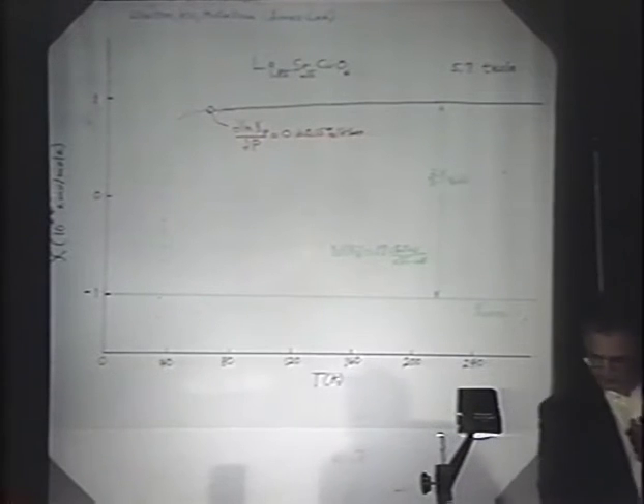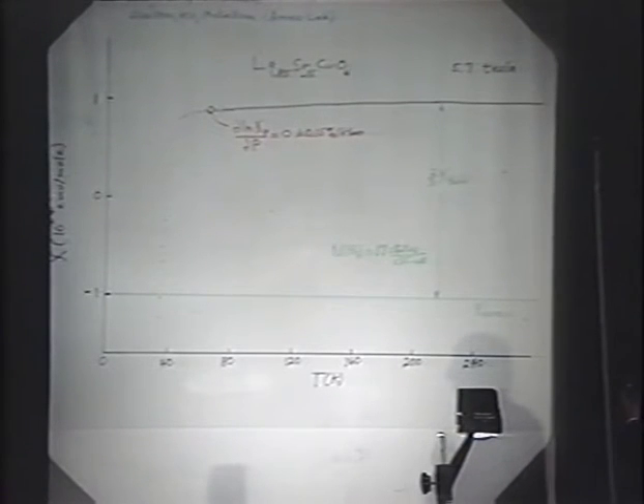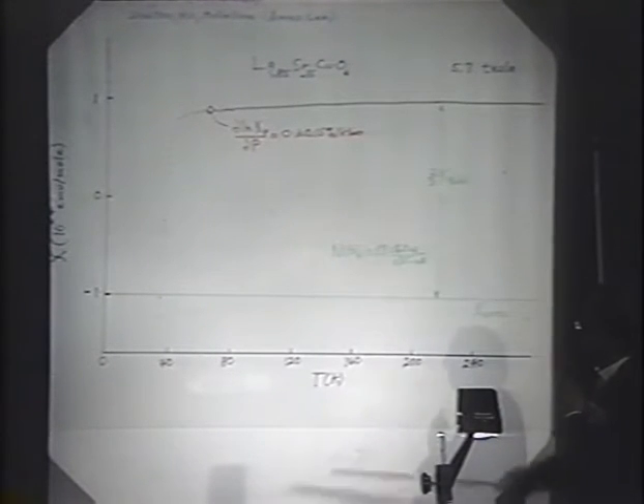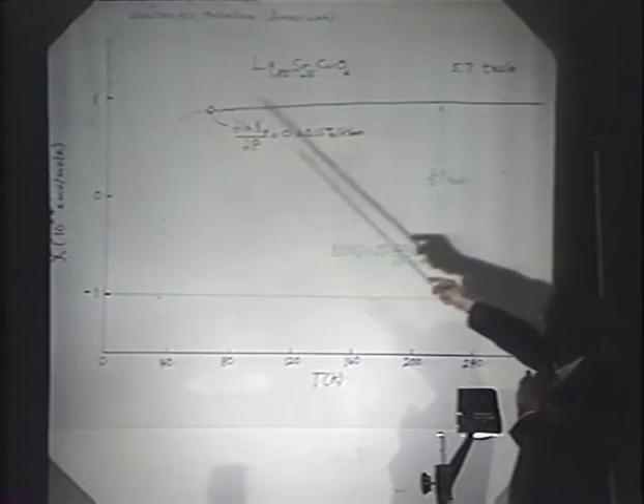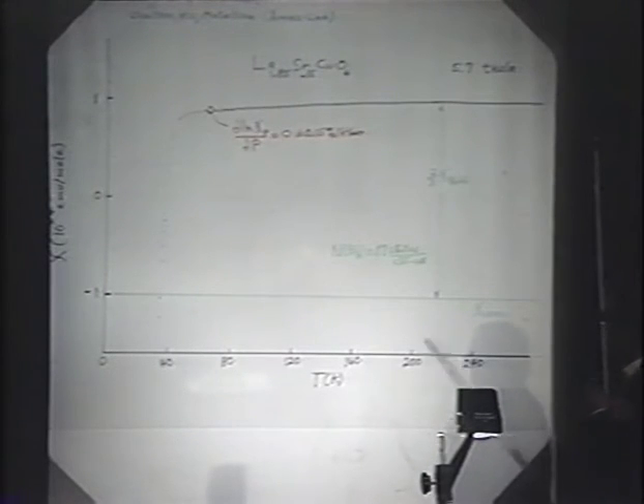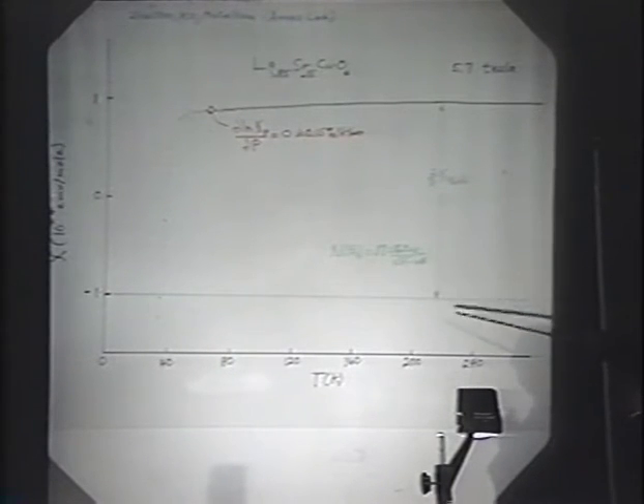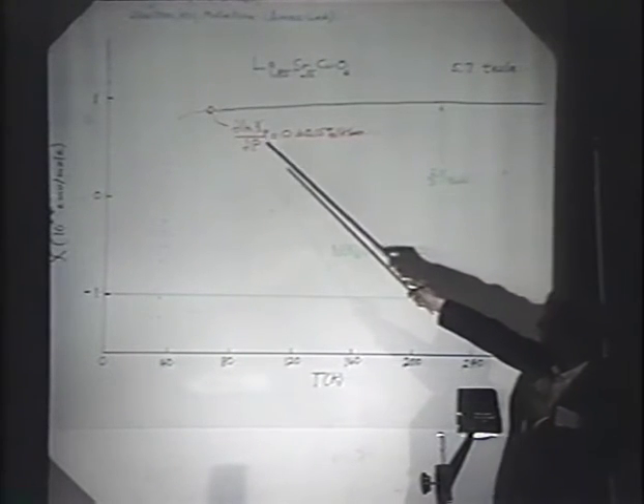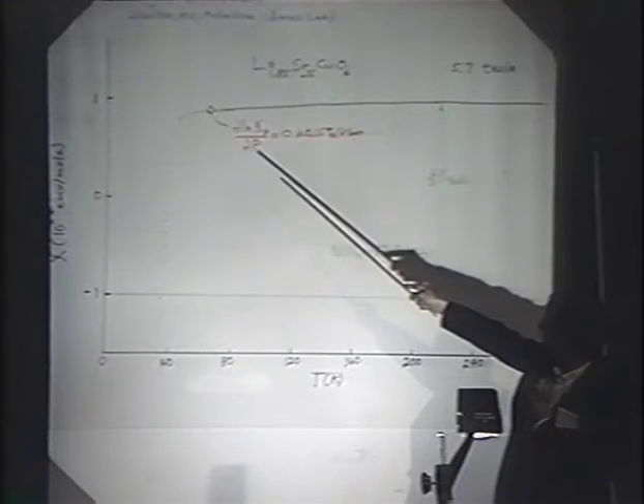Now, the susceptibility looks something like this for this compound. We've seen similar curves before as a function of temperature. It decreases slightly with decreasing temperature. Here you see the superconductivity setting in. This is at about a field of 6 Tesla. We have to subtract off the core diamagnetism, which is sitting down here, so this difference between the two curves is the susceptibility. Now, we've measured both at room temperature and at 70 degrees, so just above TC.